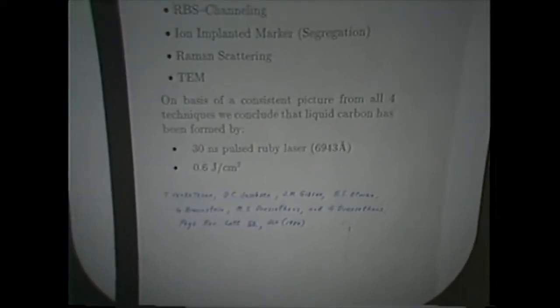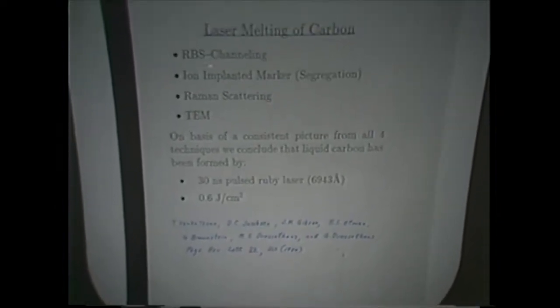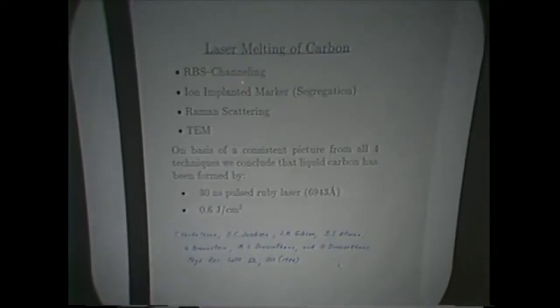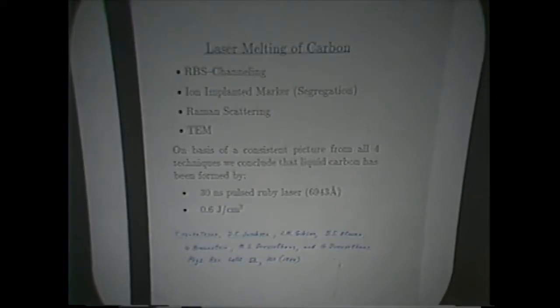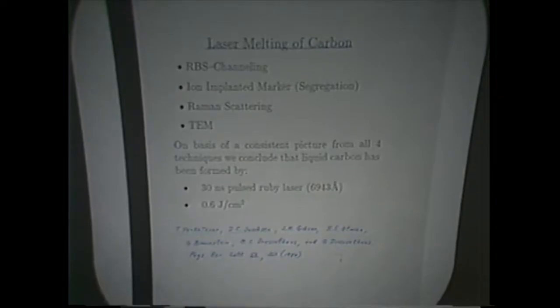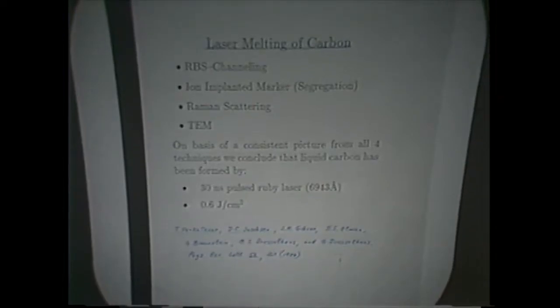And we did 4 different experiments initially to show that you can make liquid carbon. One of them is Rutherford backscattering in the channeling mode. And then we put in ion-implanted markers, Raman scattering, and transmission electron microscopy. None of these experiments by themselves were especially convincing that liquid carbon had been formed, but taken all together, there was no way that we could explain all the results without the formation of liquid carbon.